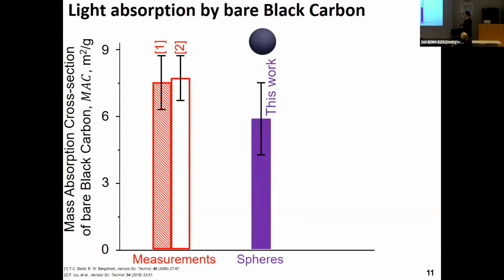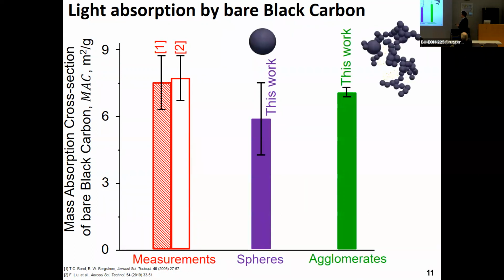So first of all, here is the classic model for spheres, where you can see that it underestimates the measurements as expected by 20%, because it neglects the porosity of these nanoparticles. And here is the mass absorption cross-section that is obtained by our new model that accounts for the fractal-like morphology of black carbon. Because, as I said, we account for the trapping of the light in this porous structure, you can see that we improve significantly the agreement between modeling and data.